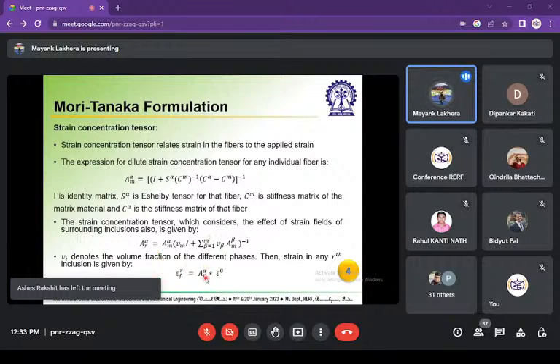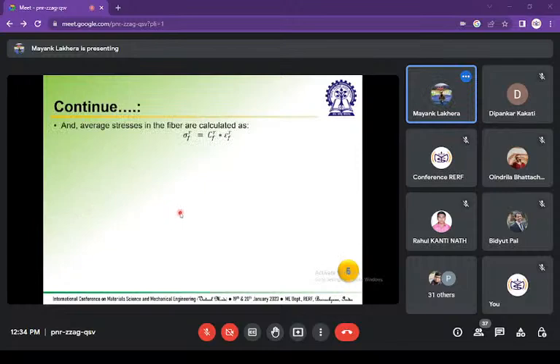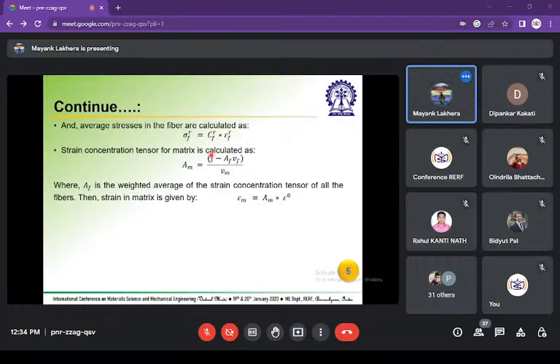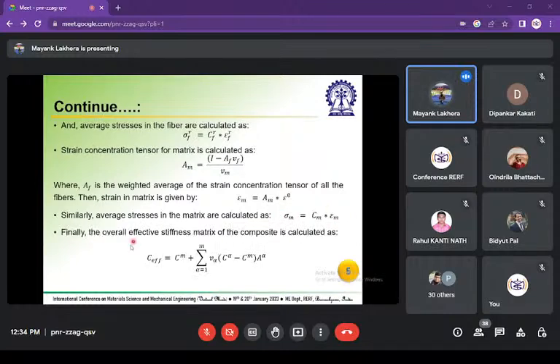And then the strain in any particular inclusion is given by this strain concentration tensor, and epsilon naught is the externally applied strain. Now we have the strain in that particular fiber, so we can calculate the stress in that fiber. And this is for the fibers. To calculate the strain concentration tensor for the matrix, we can calculate it this way. And again in the same way, we have the strain in the matrix and then the stress in the matrix by this method.